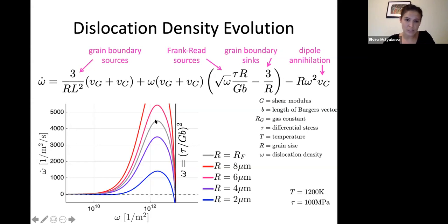So if you're a grain whose size is much larger than this, you are predominantly deforming by dislocation creep. When you're predominantly deforming by dislocation creep, you'll be here, and you'll notice that this equation, this omega dot, has a steady state. This is where these curves cross the zero line. For grains that are close to or larger than this field boundary, there is only one steady state, this black line here where omega dot crosses zero. This is the steady state dislocation density, which would be your dislocation density if you go out and observe a rock and assume it's at steady state. This will be the dislocation density you expect to find.